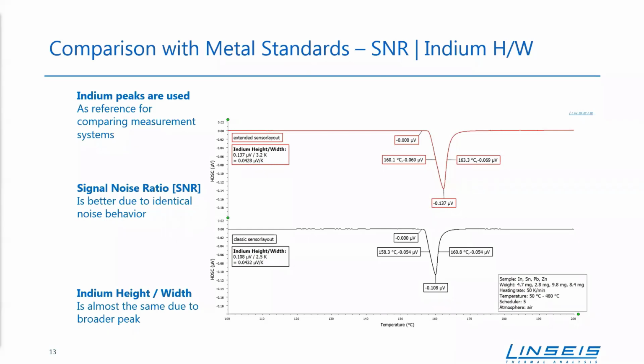As you can see there, it's for the extended sensor layout 0.137 to 3.2 Kelvin. And this is how we calculate the indium height to width ratio. And what we can see here is that they are basically the same, almost the same.